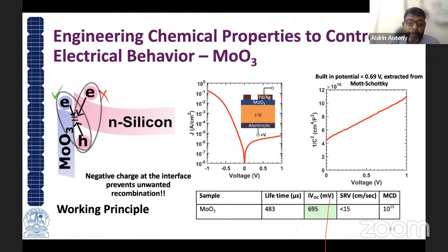It's very comparable. And if you look into the lifetimes, before fabricating the solar cell, we measured the minority carrier lifetime in the device after the MoO3 deposition. It was near 500 microseconds. And if you make a solar cell without any metallic contacts, the predicted implied VOC is near 695 millivolt.